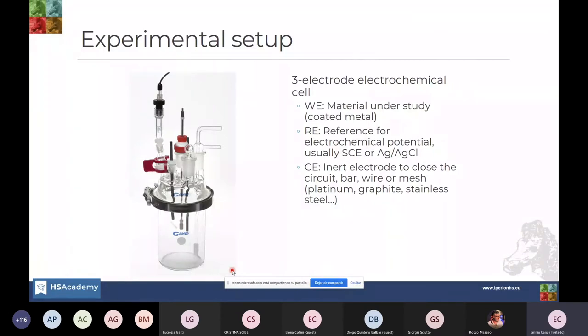We use a reference electrode for measuring the potential, which is typically a saturated calomel electrode or a silver chloride electrode. This is a reference electrode that we use to measure the potential against. And we have finally the so-called counter electrode, which is an inert electrode to close the circuit and to apply the signal. We do not want to apply our signal through the reference electrode. We can damage it or polarize it and have a wrong potential. So we use for that an external electrode, which is typically a platinum, graphite, or stainless steel layer or grid.